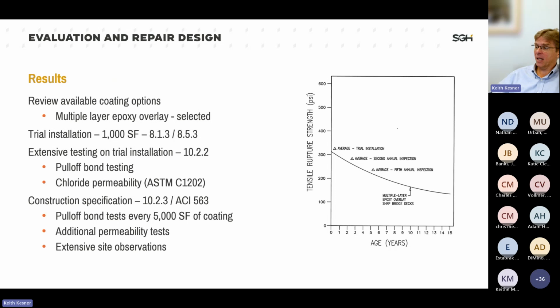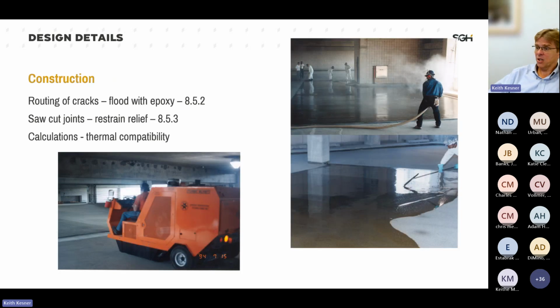The graph, some of you may recognize the graph. It's from the SHRP program, the original one, not SHRP 2, where they looked at different performance options for bridge decks. And this is actually a lucky project for me. This is some of our construction pictures. We flooded the cracks with the epoxy. We took some restraint. We added in some saw cuts, did a lot of calculations, to make sure our thermal compatibility was working.